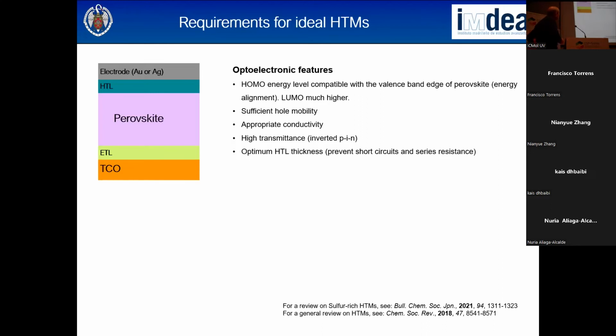Sufficient hole mobility, appropriate conductivity, high transmittance. This is in the case of the inverted structure, because you need the transparent electrode. And then the right thickness. But other chemical features are also important to consider. Good solubility, to prevent the formation of pinholes, which decreases the efficiency.